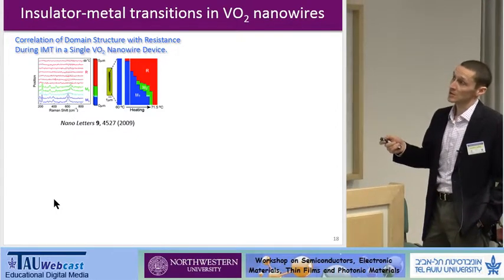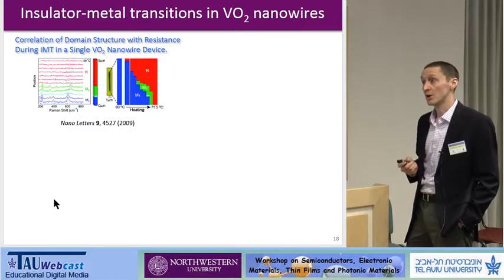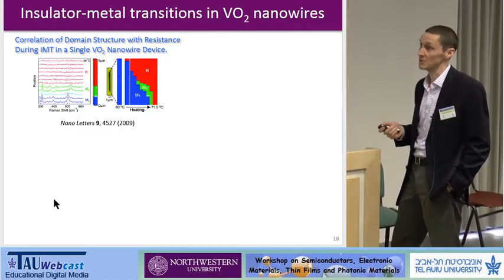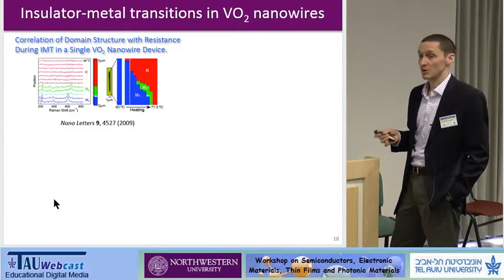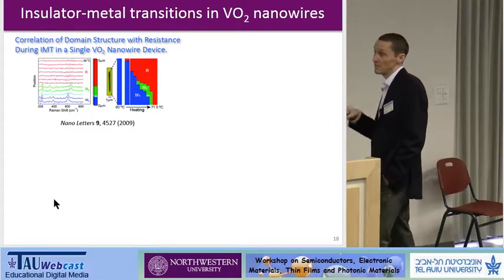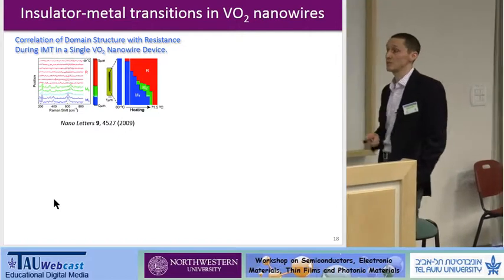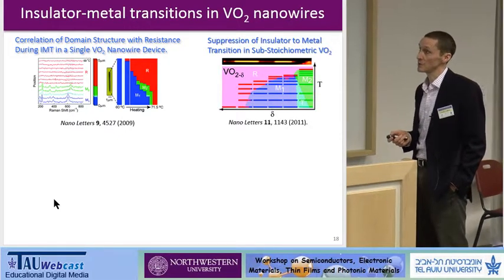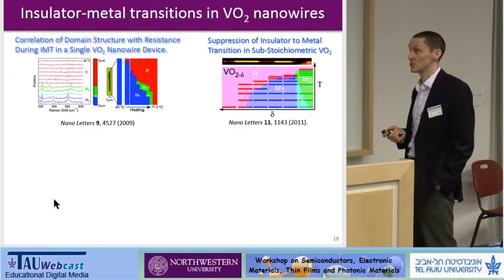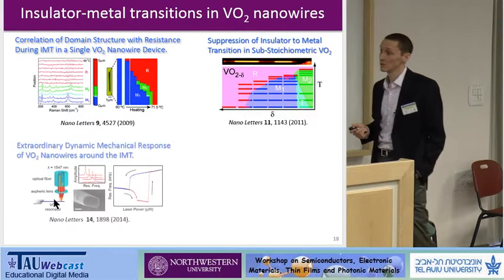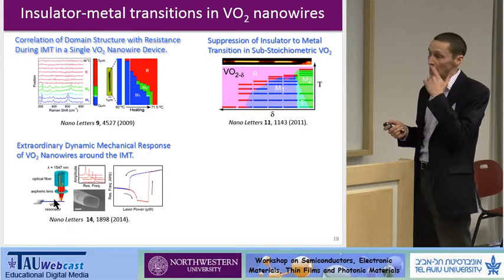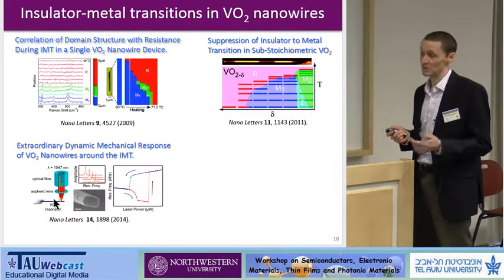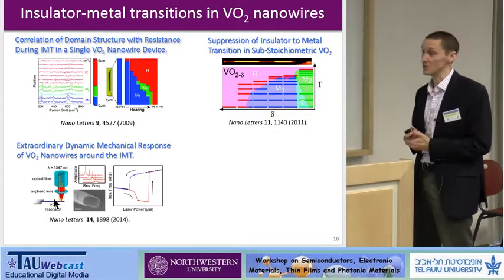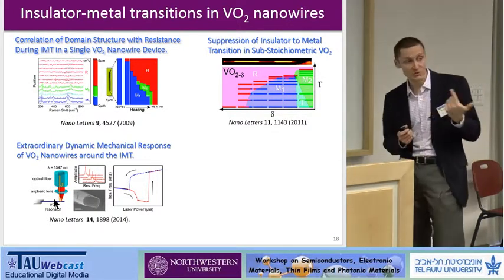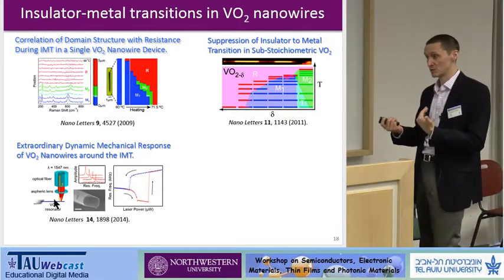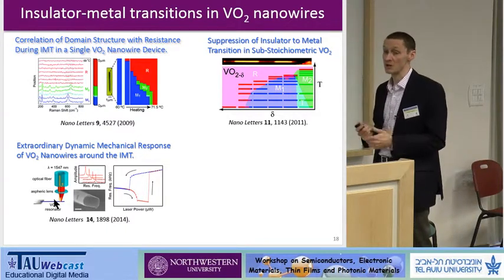So we spent a few years looking at VO2 nanowires and studying the metal insulator transition by various means. So we did some work using Raman spectroscopy to track the structural phase transition while measuring it electrically in devices. These are in single nanowires, looking at suppression of the insulator to metal transition by controlling stoichiometry. More recently, nanomechanical measurements. So looking at the mechanical properties of essentially single nanowire cantilevers as they go through the phase transition. There's some really interesting dynamics and changes in how the photons behave.